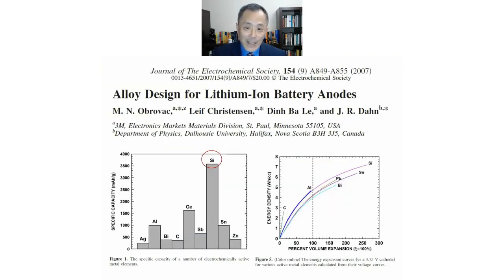Today, there's a worldwide R&D activity to further develop the lithium-ion batteries, to have higher energy, more power, lower cost, and safer. There are many materials that are known to have higher capacity than the graphite negative electrode. Showing here, for example, is silicon. Silicon theoretically can have 10 times higher capacity than that of graphite. However, silicon, like many other high capacity materials, will experience very large volume changes as lithium enters into the silicon and as it comes out of silicon. The volume change can be as large as 300%.